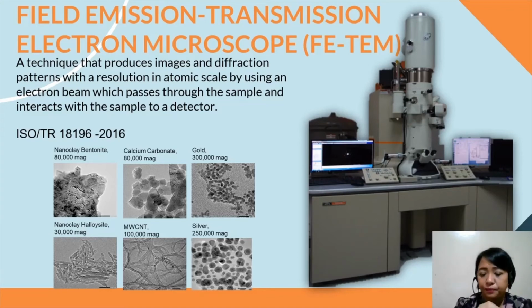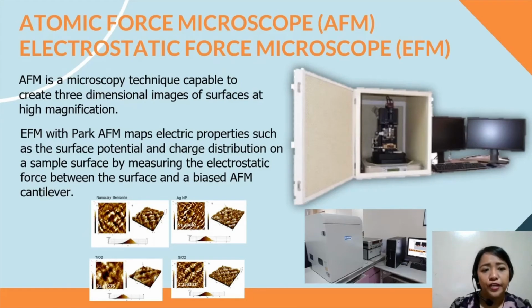Our laboratory has the atomic force microscope and electrostatic force microscope by Park Systems, where the AFM is a microscopy technique capable of creating three-dimensional images of surfaces at high magnification, and EFM with Park AFM maps electric properties such as the surface potential and charge distribution on a sample surface by measuring the electrostatic force between the surface and a biased AFM cantilever.